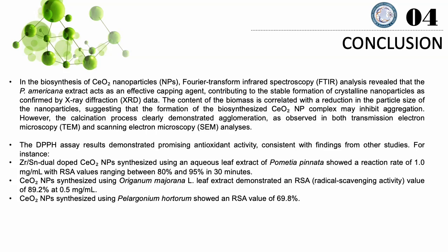The DPPH assay results demonstrated promising antioxidant activity, consistent with findings from other studies. For instance, zirconium-tin dual-doped cerium oxide nanoparticles synthesized using an aqueous leaf extract of Pometia pinnata showed, at 1.5 milligrams per milliliter, radical scavenging activity values ranging between 80% and 95% in 30 minutes.